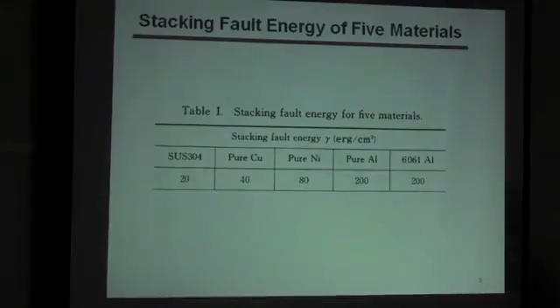The first one is a very old research, about 25 years ago, when Ito was a graduate student in my lab, and I asked him, okay, pick up 5 materials with different stacking fault energy, and we will make a non-proportional loading, and draw what kind of additional hardening happens in each material. And we selected 5 materials. One is stainless steel, the lowest stacking fault energy material, 20 mJ per square meter. And pure copper is a little bit higher, 40. And pure nickel, it was a very expensive material, but we bought it, for 80. And pure aluminum and 6061 aluminum, whose stacking fault energy is 200.